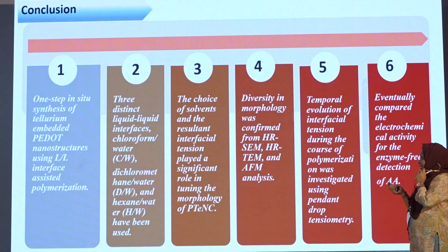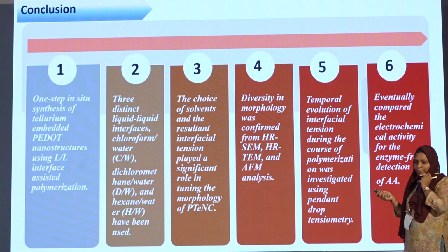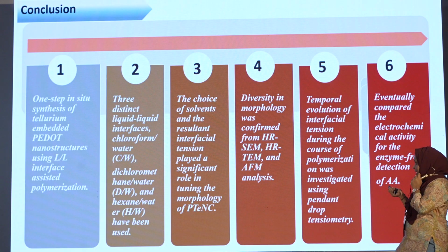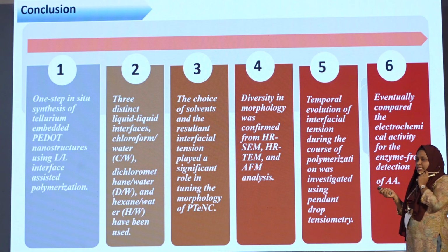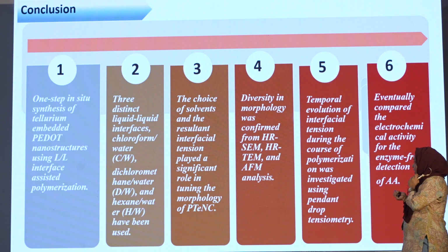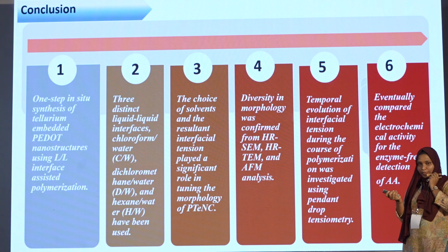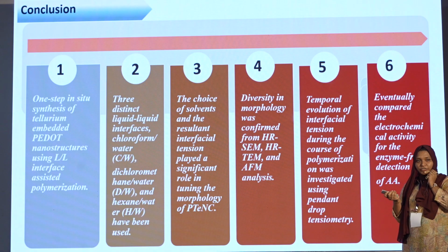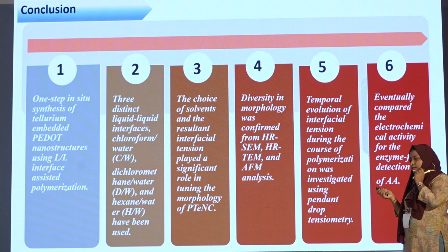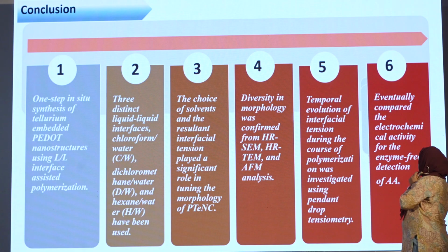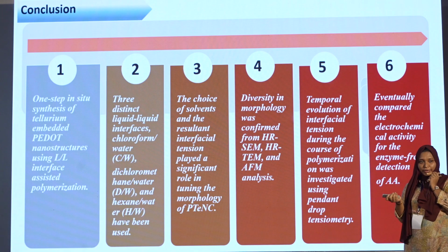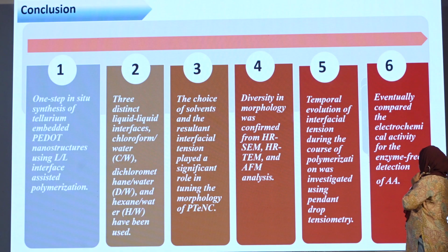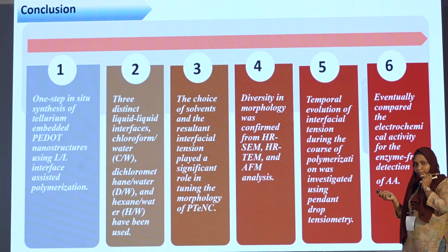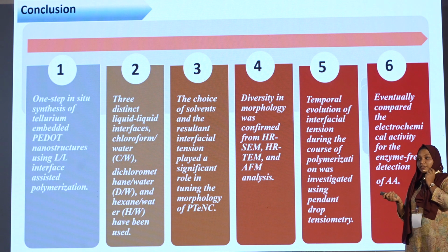So in conclusion, one-step in situ synthesis of tellurium embedded PEDOT nanostructures using liquid-liquid interface assisted polymerization has been done. Three distinct liquid-liquid interfaces of chloroform-water, dichloromethane-water and hexane-water have been used. The choice of solvents and the interfacial tension played an integral role in determining the morphology of the structures. Diversity in the structures was confirmed from HRTEM and AFM analysis. Then the temporal evolution of interfacial tension during the course of polymerization was analyzed using pendant drop tensiometry, and this was eventually compared for its electrochemical activity towards the enzyme-free detection of ascorbic acid.